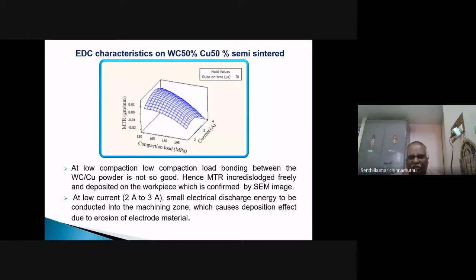and the current. At low compaction load, the material deposition is higher. But in case of higher compaction load, the material deposition is lower. Why? Because at lower compaction load, the bonding between the materials, that is the copper as well as the tungsten carbide, is very less. So it dislodges freely and is deposited on the workpiece. And at low current, the amount of electrical energy conducted in the machining zone is very less, which causes deposition of the electrode.